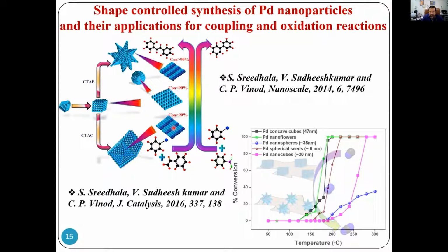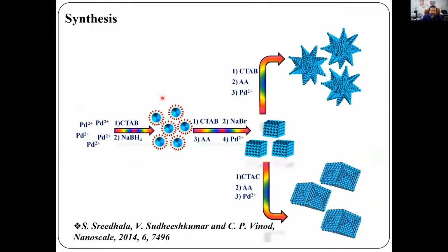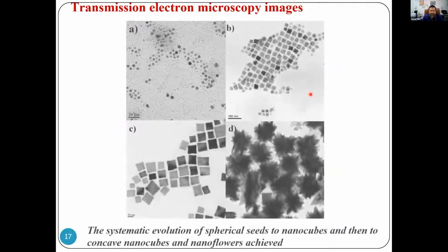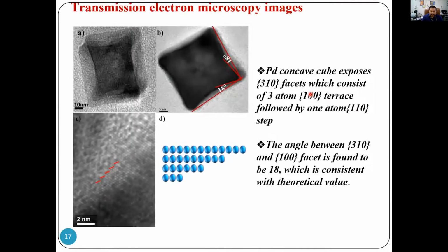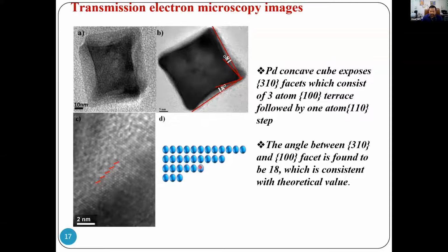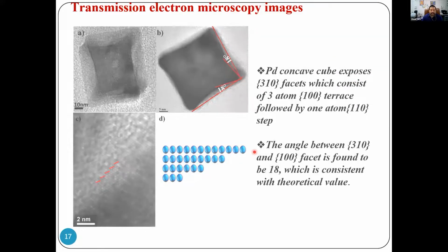And we have actually run two reactions with this catalyst. One is basically a CO oxidation reaction like what we did previously with the gold nanoparticles, and the other one is Suzuki and Heck coupling reactions. So again, the synthesis procedure has been reported in Nanoscale in 2014. So if anybody is interested, can have a look at the synthesis procedure. Again, electron microscopy has been done to characterize this, and you can see that there is a concave surface that is formed when you make concave palladium nanocubes. And these are the ones which actually carry 310 undercoordinated surface atoms.